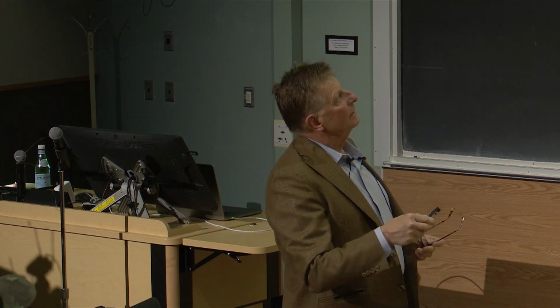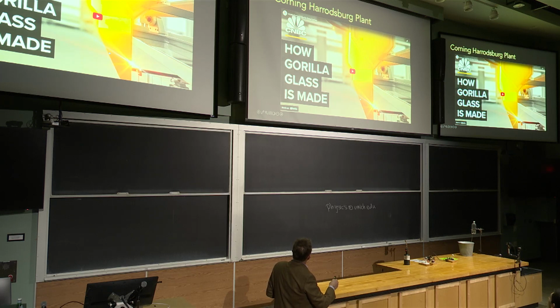The glass is melted and then it enters this trough, and then it overflows on the edges on both sides, and it runs, and this is made out of platinum, it's very expensive. Then it runs and sticks to the wall, and the two sides now combine. The thing is that the surface of the glass, as it ends up being, has never been in touch with anything else. Right, so it's a very pristine surface, and then the ion exchange happens, and you get that really strong glass that you have in your devices.